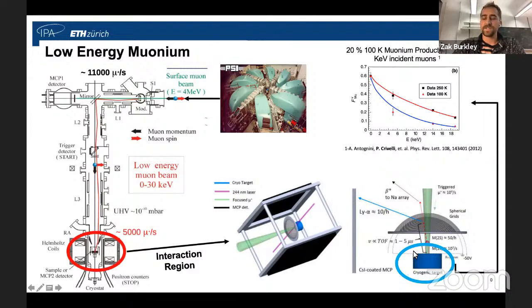And in this interaction region, as we talked about, we'll have this cryogenic target. We will have our high power 244 nanometer laser and our Lyman alpha detectors and quenching electrodes. And what I'd like to show you here on the top right is work that has been done in the past at this LEM beamline, that for 5 or 6 keV incoming muons hitting this 100 Kelvin cryogenic target, the conversion to muonium is 20%. And this is very good. And this is into vacuum. And this is our check mark number 1. We have this low energy muonium at high yields, which is important for the CW spectroscopy.